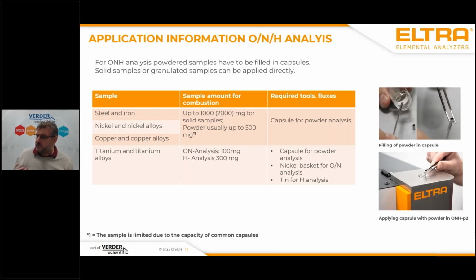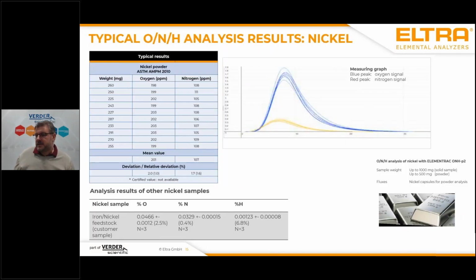And the application of different forms is easy. A solid sample is applied directly to the furnace, and powders or drilled samples just have to be applied in capsules. Yeah, and that's it. Typical results again look like this. For oxygen and nitrogen determination, you can have a simultaneous measurement, which means here you have a blue curve, which is the measurement of oxygen. Then we have the yellow curve, which is the measurement of nitrogen.